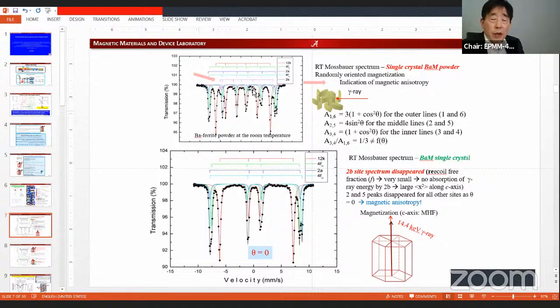In this complicated system, we can apply the magnetic field in the direction of the gamma ray or perpendicular to it, and some of the peaks will disappear. Because of this, we can understand magnetic property changes and the magnetic hyperfine field changes with a substitution site or interstitial site in the case of hexaferrite.